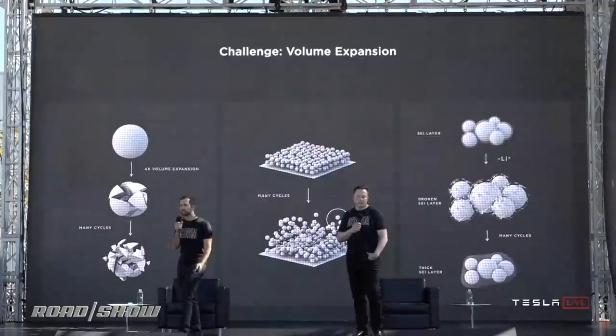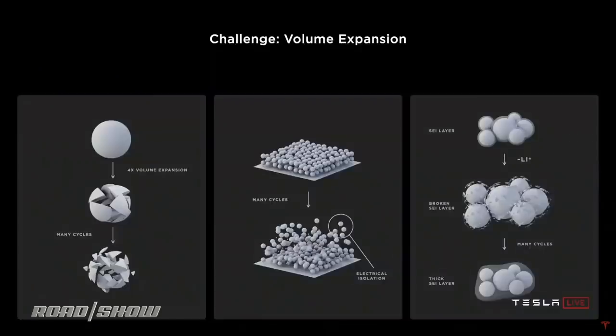The main reason is because the challenge with silicon is that it expands 4x when fully charged with lithium. And basically, all of that expansion stress on the particles start cracking, they start electrically isolating, you lose capacity, the energy retention of the battery starts to fade, and it also gums up with a passivation layer that has to keep reforming as the particles expand.